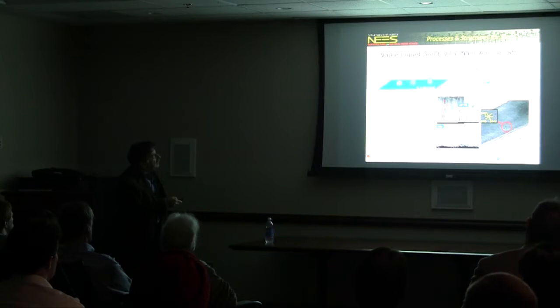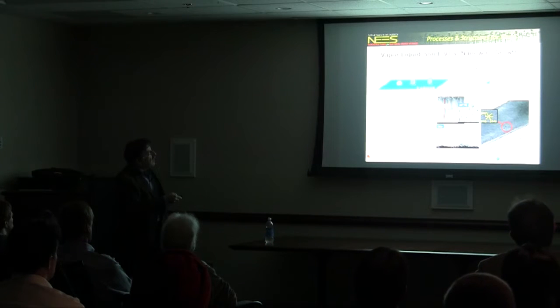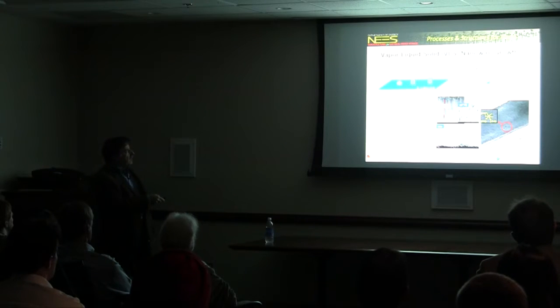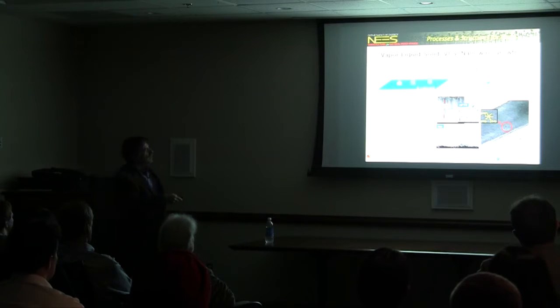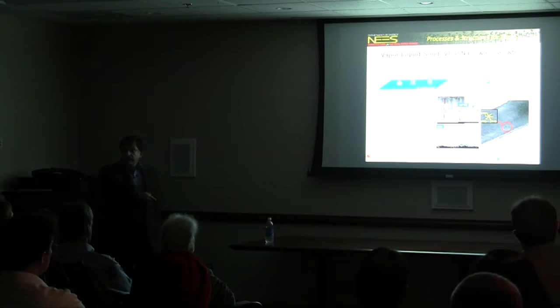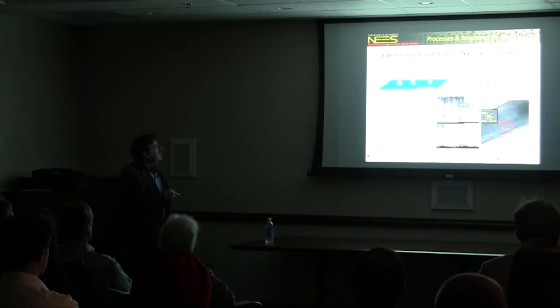What you see here is a 1500 nanometer silicon germanium alloy nanowire. It's only 40 nanometers wide. And you can make forests of these things, as you see here. And if you look very closely, these are perfect crystals. So they're really very nice structures to work with. This is a collaborator, Tom Picraux, at Los Alamos National Lab.